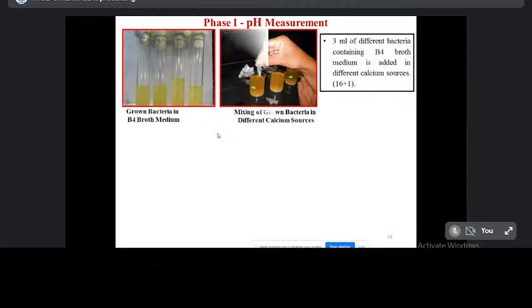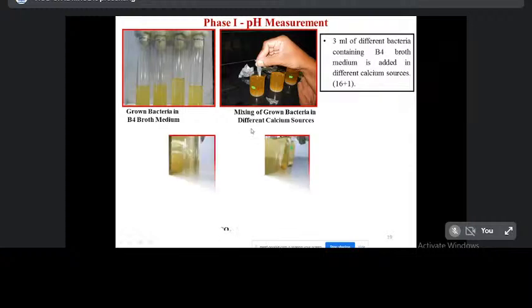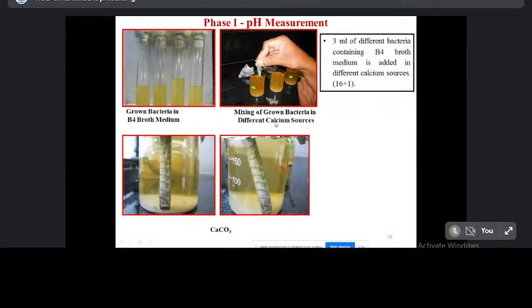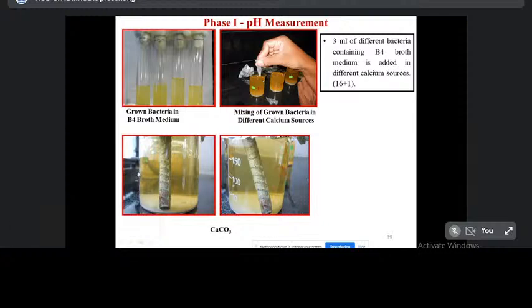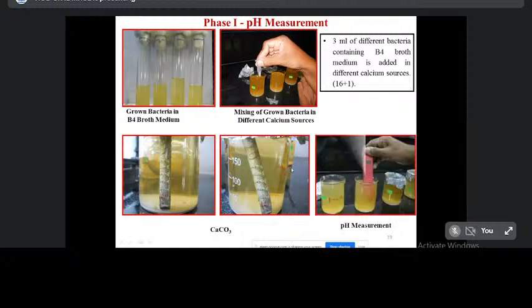This first slide shows the grown bacteria in B4 broth medium. Then mixing of grown bacteria in different calcium sources. The second slide shows the mixing process. After mixing the B4 broth medium of bacteria, after 24 hours, we have observed some white deposit on this rod, right? So this is the calcium carbonate. After that, I have measured the pH.